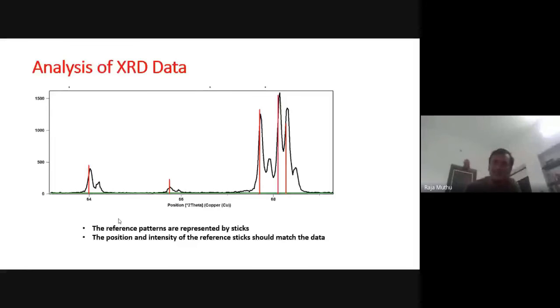So now, how to analyze the XRD data? See the peaks. The green color is what? The peaks observed by conducting the experiments with the XRD machine. Whereas the red lines are the peaks from the database provided by JCPDS. These two have to be compared. After taking the XRD spectra, it has to be compared with the reference. Each and every peak of the reference and the sample should be matched. Here it almost matches. The reference patterns are represented by sticks. The position and intensity of the reference stick should match. It's almost matched, so it can be accepted, and we can say this is so-and-so substance.